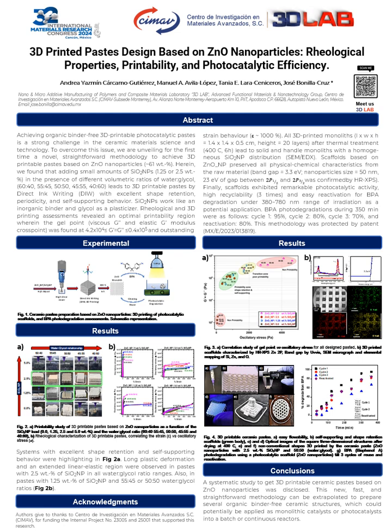The scaffolds exhibited remarkable photocatalytic activity, high recyclability, three times, and easy reactivation for BPA degradation, under the 380 to 780 nm range of irradiation, as a potential application. BPA photodegradation during 350 min was as follows: Cycle 1, 95%; Cycle 2, 80%; Cycle 3, 70%; and reactivation, 80%.